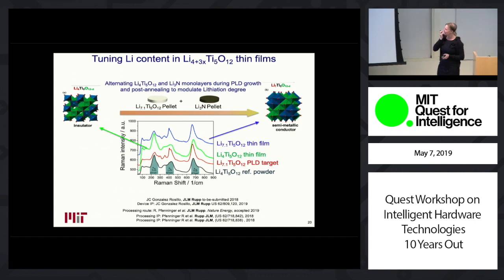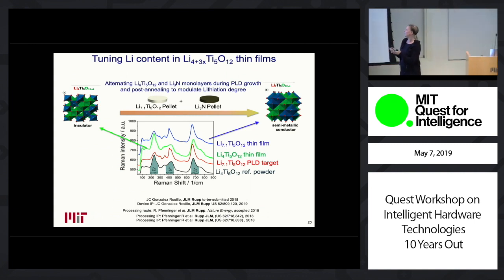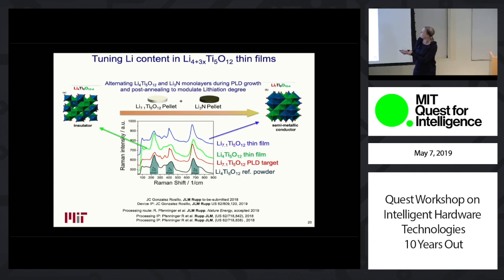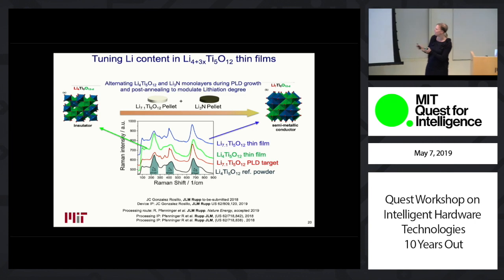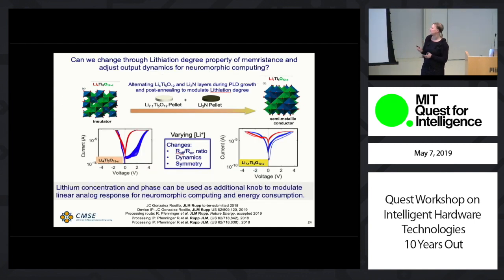And here comes the result. To show you, just for the record, that we can actually make both phases in thin film: yes, we can. We can see that in the Raman, looking here at lithium-oxygen and titanium-oxygen bonds. But cutting to the chase, this has a huge impact on the switching. Here's a memristor response for the low-lithiated and the high-lithiated phase. So you see the current-voltage response.